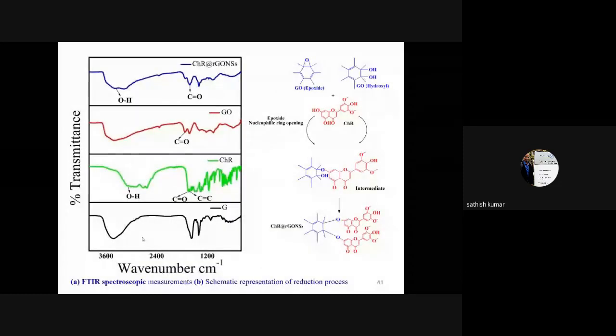Here also, as we have used a single flavone, we are able to predict the mechanism of reduction, that is, the conversion of graphene oxide into reduced graphene oxide. As I mentioned earlier, the graphene oxide has oxygen functional groups like epoxide and hydroxyl groups. Here chrysin will act as a nucleophile, and through the epoxide nucleophilic ring opening mechanism, the oxygen functional groups will form an intermediate, and then the chrysin functionalized reduced graphene oxide will be formed.